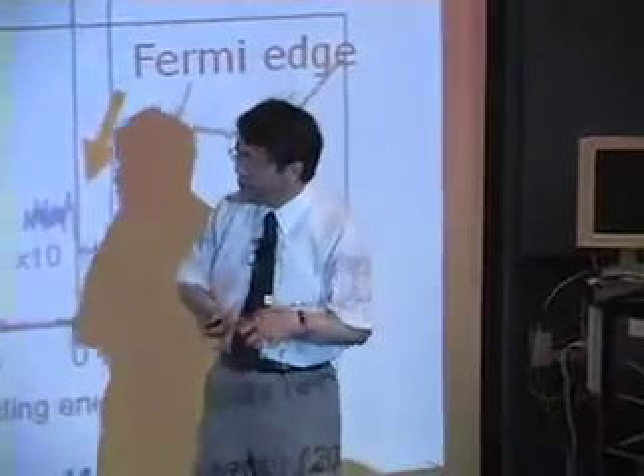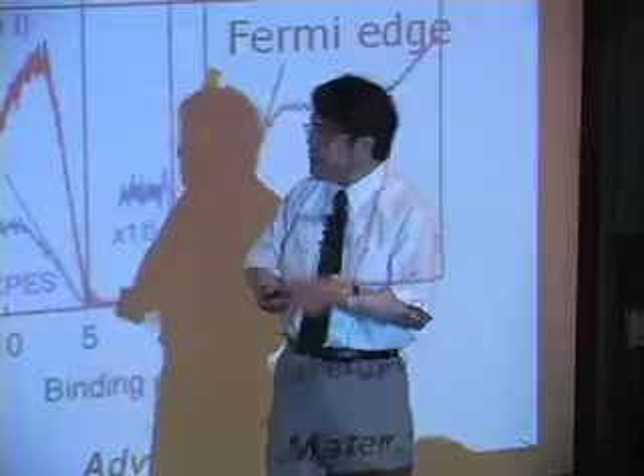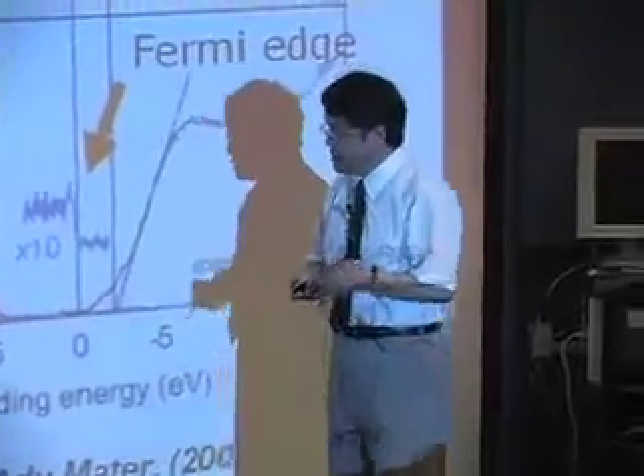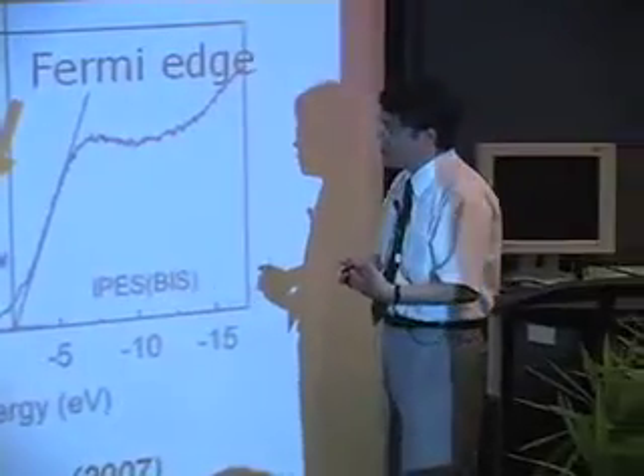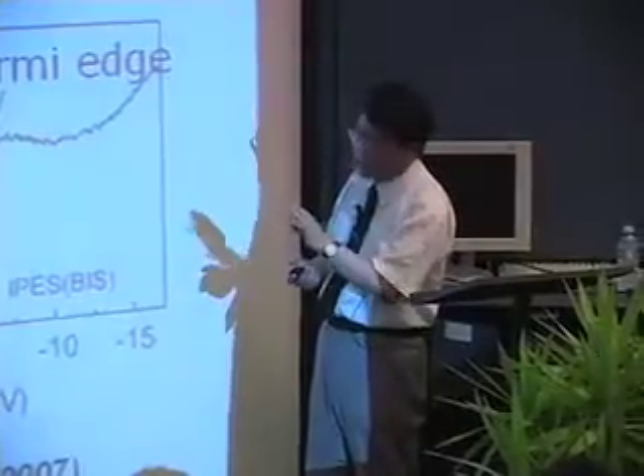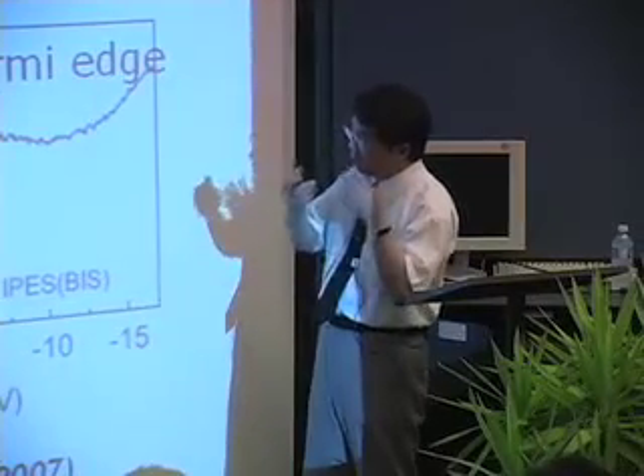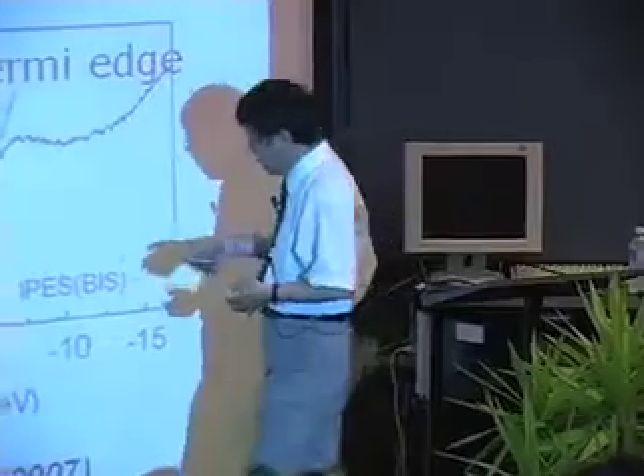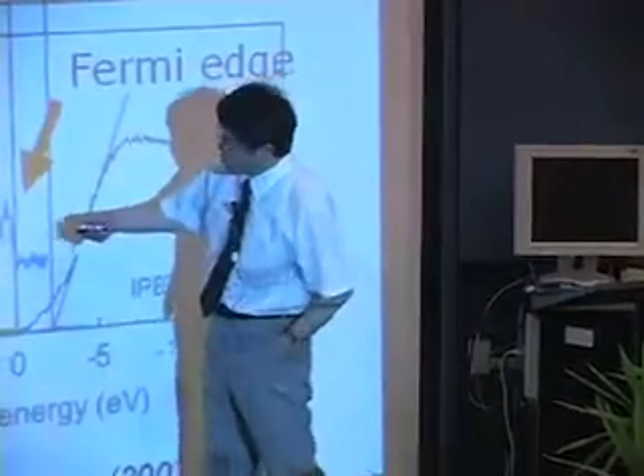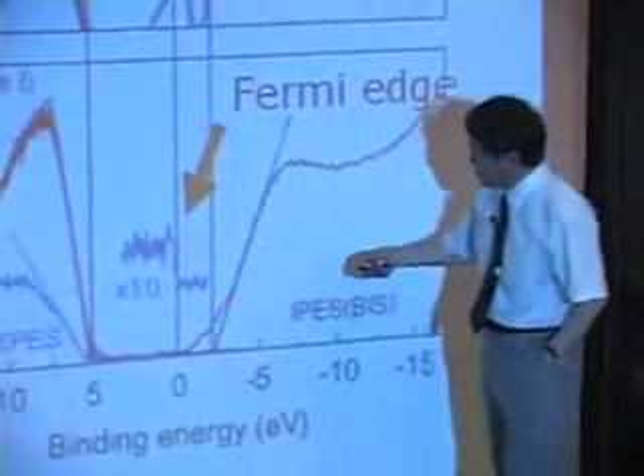So we adopted hard X-ray PES as the excitation source, which is bulk sensitive, not so surface sensitive, so we can get reliable data. This is the top of the valence band, and this is the bottom of the conduction band.